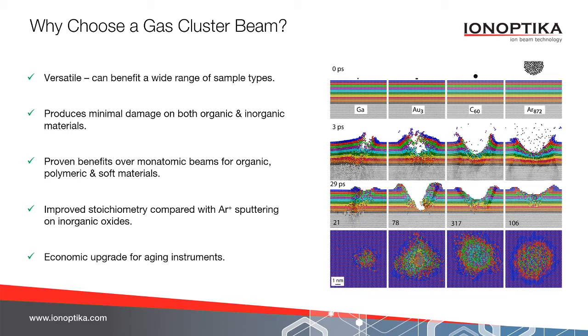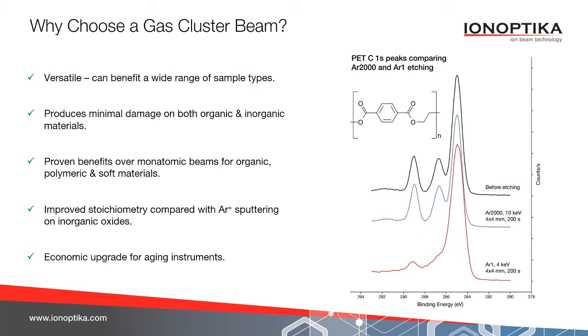So comparing to a monatomic argon beam, if we look at a PET spectrum from an XPS, we look at the C1s peaks, these two peaks here, which are the carbon-oxygen bonds, after sputtering with an argon-1 beam, these peaks have almost disappeared. So those bonds have been broken. Whereas if we compare the pristine sample, which is this black line here, and the argon cluster sputtering, they're almost identical. So the carbon-oxygen bonds have not been broken. And this is the benefit of argon clusters.